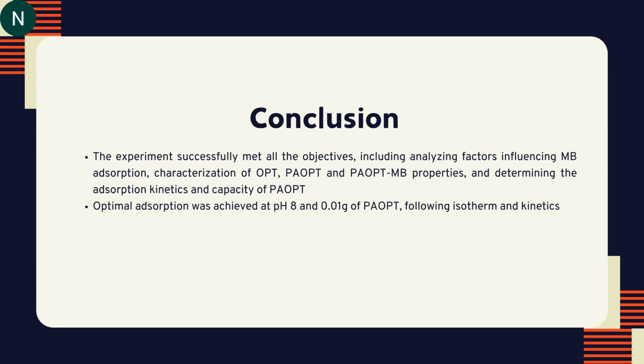So for the conclusions, the experiment successfully met all the objectives, including analyzing factors influencing methylene blue adsorption, characterization of OPT, PaOPT, and PaOPT-MB properties, and determining the adsorption kinetics and capacity of PaOPT. And the optimal adsorption was achieved at pH 8 and 0.01 gram of PaOPT following isotherms and kinetics.